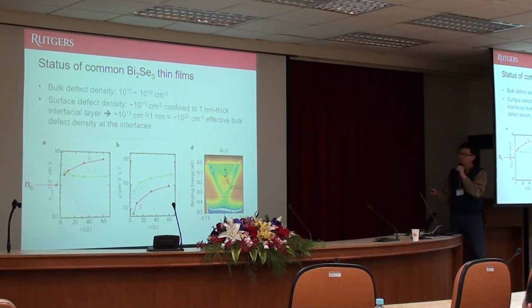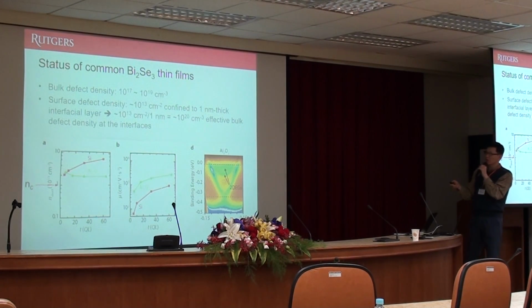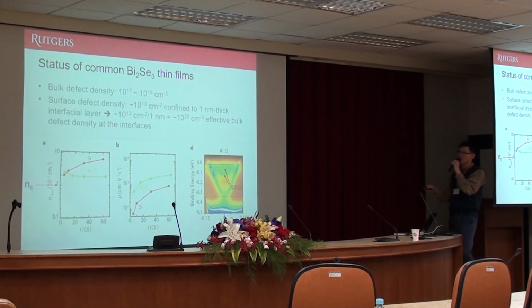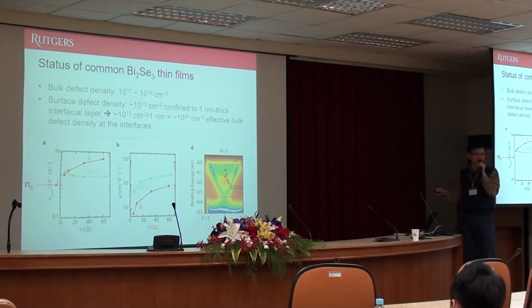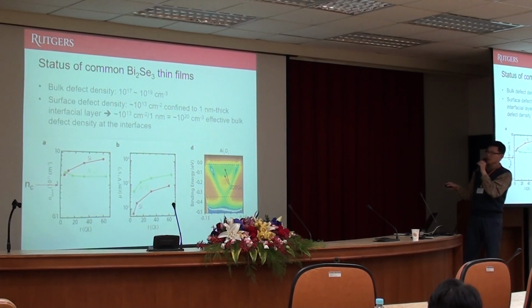So then what is the status of bismuth selenide thin films? Okay, MBE has advantages, but that does not solve the problem. There is an intrinsic advantage of MBE films relative to other growth methods, but even with that, there are still many problems. So let's see what the status is. The bulk defect density, if you grow thin films, is 10 to the 17 to 10 to the 19 per cubic centimeter. But it turns out that you have a surface defect density on the order of 10 to the 13 per square centimeter, which is equivalent to roughly 10 to the 20 per cubic centimeter if you assume that all the defects are confined to just one monolayer. So if you compare, surface defect density is much bigger than bulk defect density.